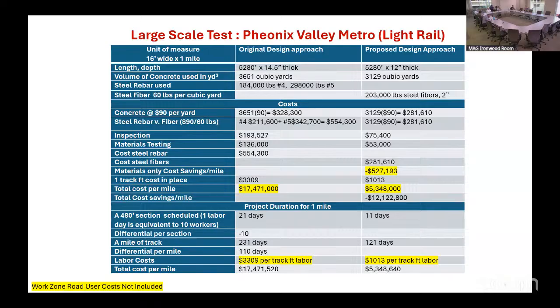So, these are the data that came from City of Phoenix, and I'll be happy to provide you with the report, a detailed analysis. Basically, we reduced some of the thickness of the concrete, 2.5 inches. We took all of the rebar out. It was about half a million pounds. About number 4 rebars, about 184,000 pounds, and about 300,000 pounds of number 5. All of that was gone, and we used 60 pounds of steel fiber for that. So basically, there is a reduction, although we were just overestimating.